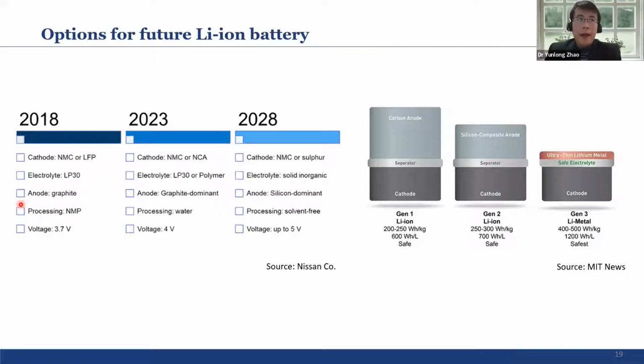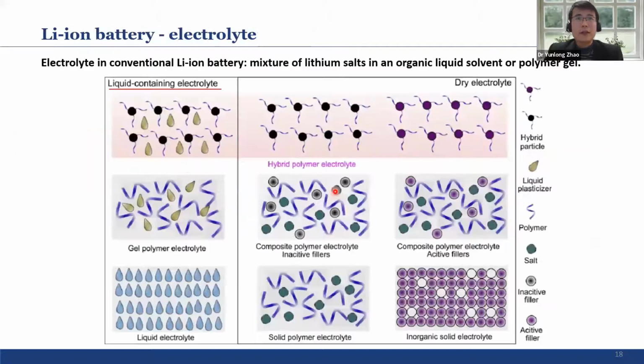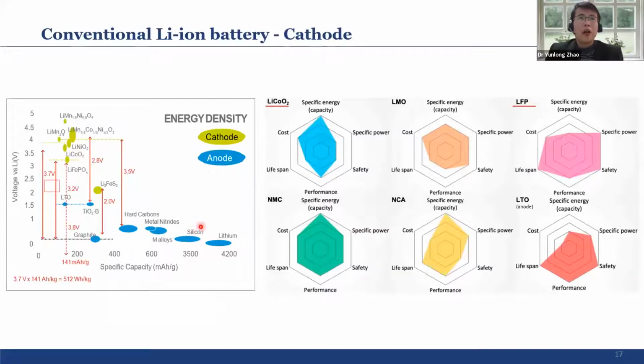For the anode, right now the commercial material is graphite, but they have already added higher energy anode materials, for example silicon, into the graphite structures. Even though at the beginning graphite may still dominate, eventually they want to use silicon as the dominant anode, because if you look at previous slides, silicon has a much larger capacity compared with graphite,